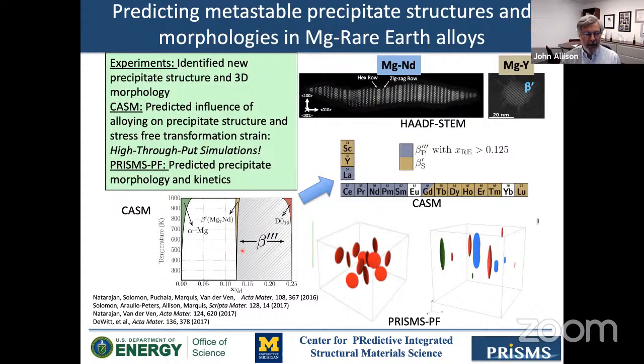Then we used CASM, and by we, I mean Anton van der Ven and his then student and postdoc, Anirudh Natarajan, who did high throughput CASM simulations and determined that these Mg-neodymium prototypes, beta triple prime, are shown here in gray. So a number of elements meet that model. And then the yttrium atoms are like Mg-yttrium and form beta prime S, which is more like this phase in the center of this phase diagram if it were Mg-yttrium. And this all has to do with the stress-free transformation strain of these particular elements in magnesium. And Anirudh was able to calculate that and propose this is the primary mechanism.